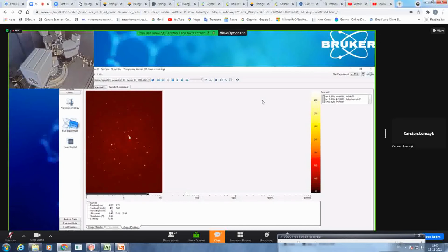In case they do, it's either twinned, or you can try to increase the detector distance. That would be the first thing I would do. You see now the spot separation, as far as you can see, is nice, so we can even decrease it. I guess we currently measure at 50. We can also decrease it to 40 millimeter, and we will still get very nice spot separation.